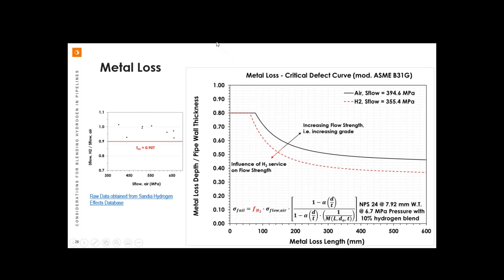Okay, our first example, metal loss. Many of these slides are structured in a similar way. What you'll find is there is a throwback basically to Christian's section where we present the degradation or the change in the material properties in hydrogen service versus air. So here you'll see on the y-axis that we have the ratio of the flow strength in hydrogen versus the flow strength in air at a number of different grades here, covering approximately grade X42 to kind of X80. So it's represented by flow strength. What we see is that we have no data points in this small data set that is below 0.9.